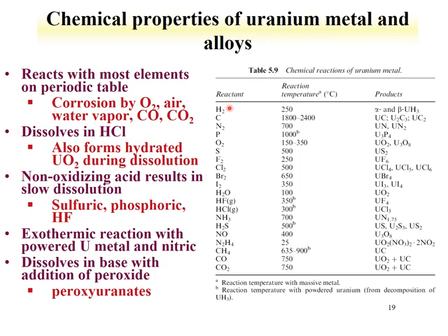And here's a review of reactions of uranium metal. Again, imagine doing this in a tube furnace. We have different reactants, different temperatures, and different products. As we talked about earlier, if we were interested in forming uranium chlorides, we can react uranium metal with chlorine gas and get a mixture of chlorides at 500 degrees. Or if we took uranium metal and reacted it with HCl, we can get the uranium trichloride at 300 degrees.